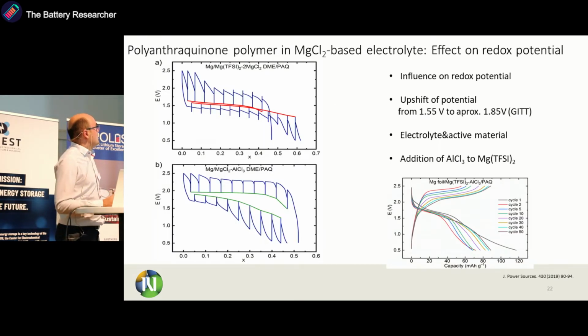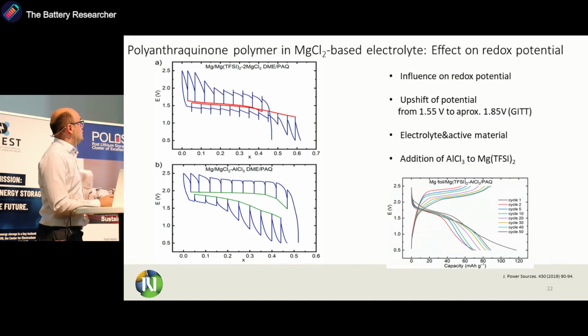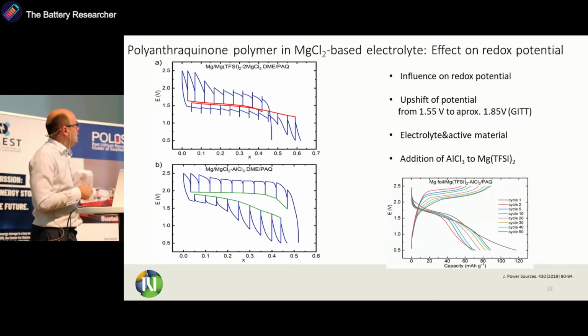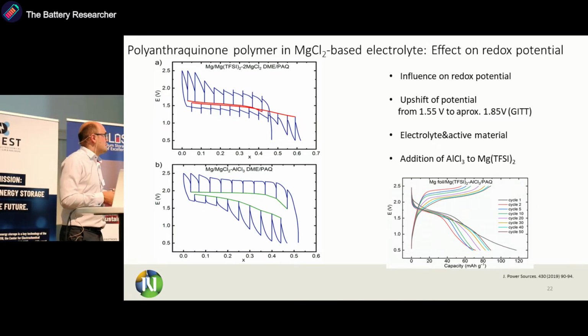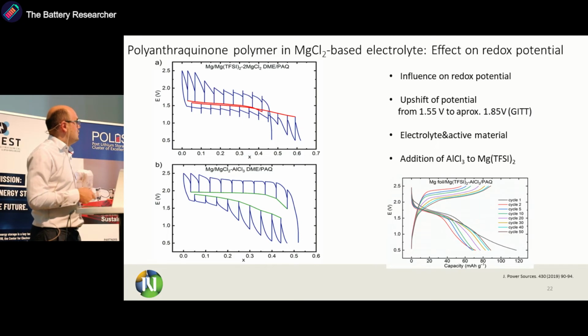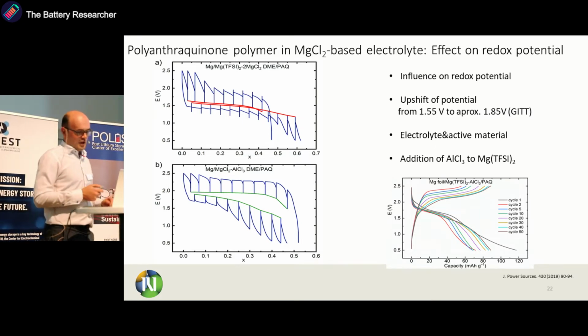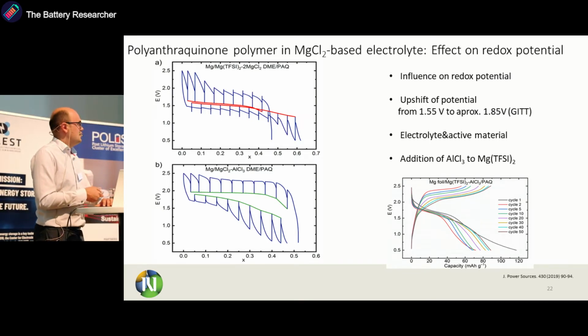Here we also investigated something else, the effect of the electrolyte on the redox potential. And when we compare the redox potential of magnesium TFSI and aluminum chloride-based electrolyte, we can see that here it's around 1.55 volts, and here it's around 1.85 volts. It means that most likely there is some kind of electrolyte and active material interplay, which somehow upshifts the potential of the electroactive group. We investigated this by adding aluminum chloride to magnesium TFSI.